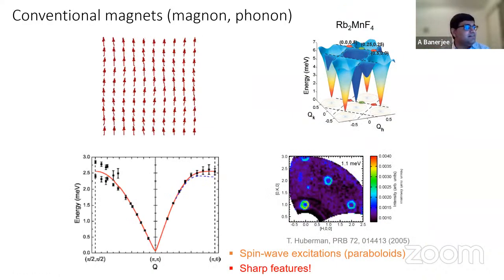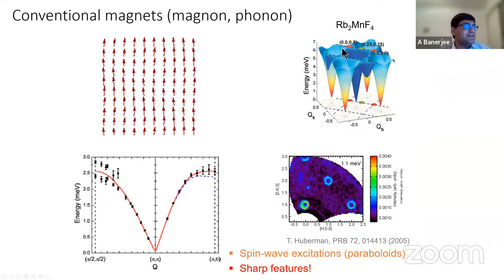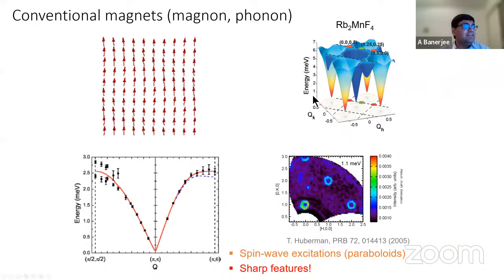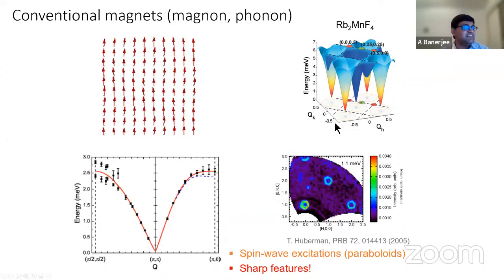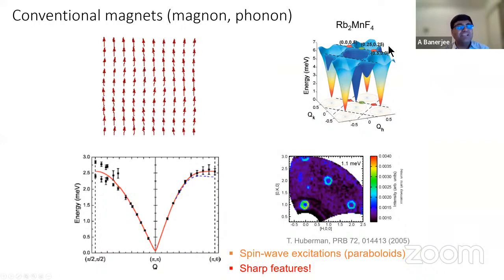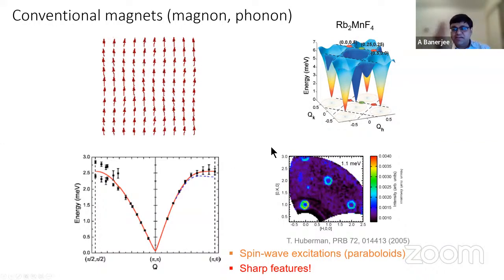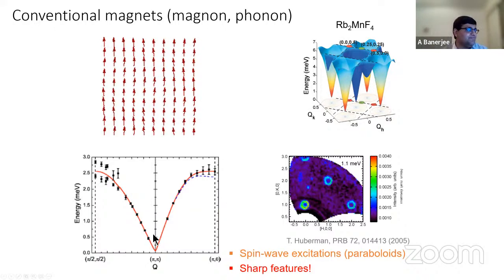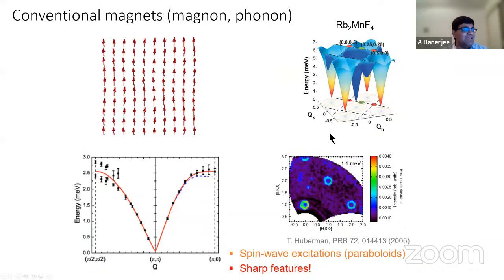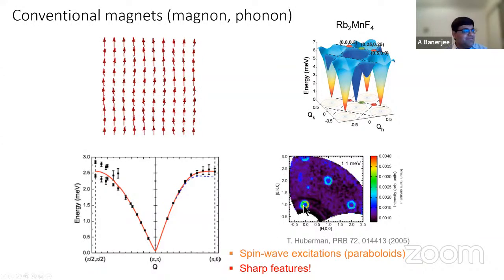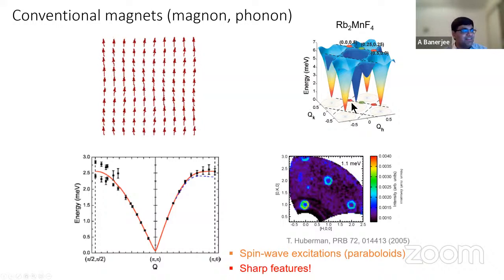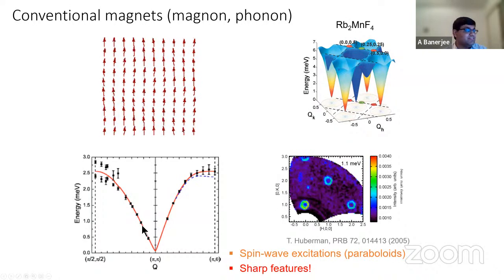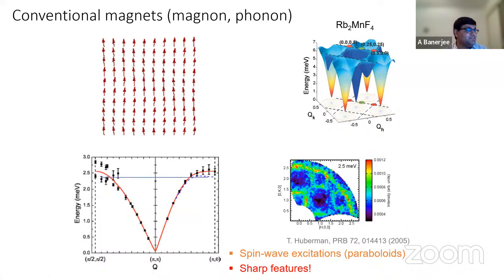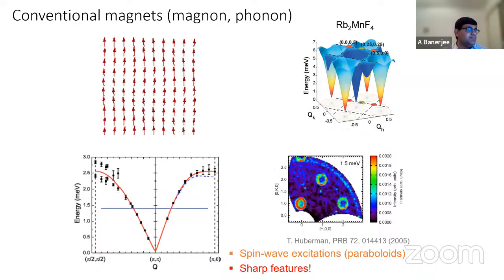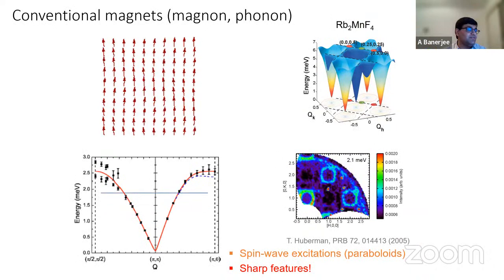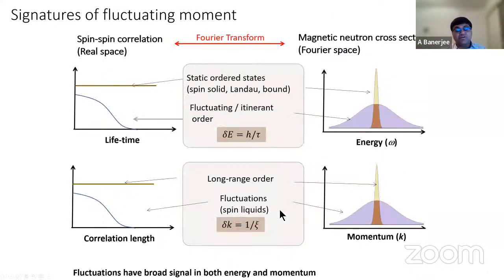So conventional magnets, what does the spectrum look like for conventional magnets? If you look at the dispersion in conventional magnets, which have magnons, if this is energy and this is the momentum axis, what you get are these cone-like features. And if you make a cut across one of these cones, you get a parabola type shape. And this is how the dispersion looks in the plane QK. So you basically get these circles, which is like you are cutting right here. If you cut one slice right here, you will get this cone. As you go up in energy, you see that these cones become bigger and smaller. So this is exactly how things look for a conventional magnet.